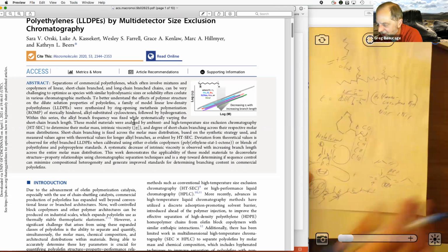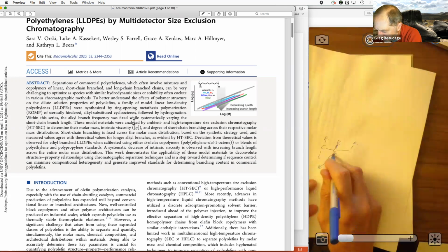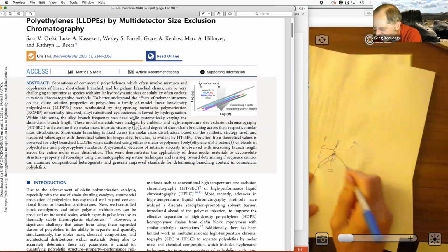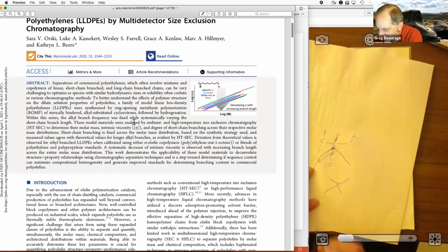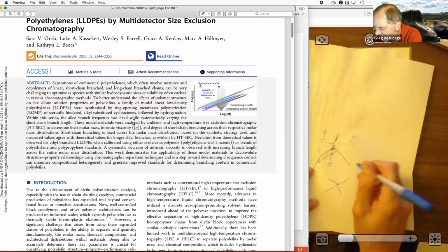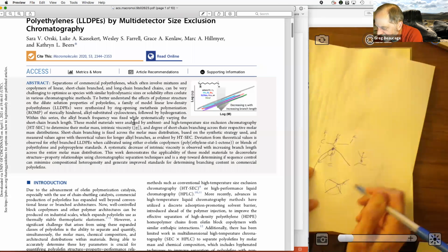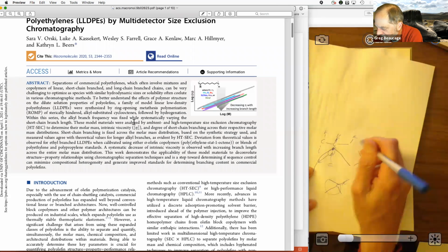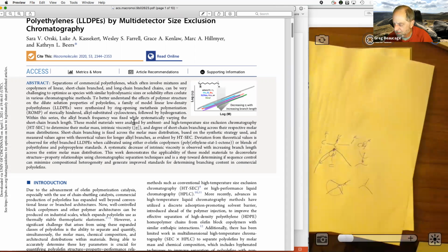So if you do a hydrogen abstraction, those can react, and then it can make like a three-way bond here, a four-way bond. So you can have like the carbon and like that. Or you could have another free radical. So two of these can combine, and that also makes a four-way bond. Right? Or you could have an abstraction from the methyl group at the end, and that would make a three-way bond. Right? So you're going to get branching. You could possibly get branching from this reaction.